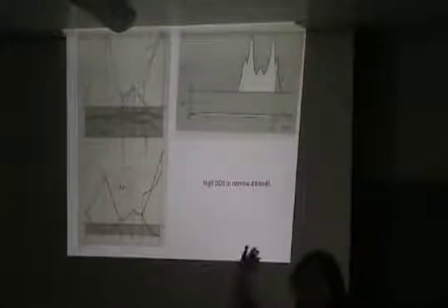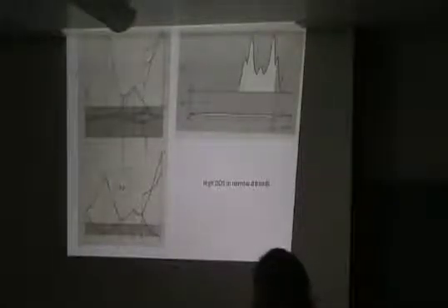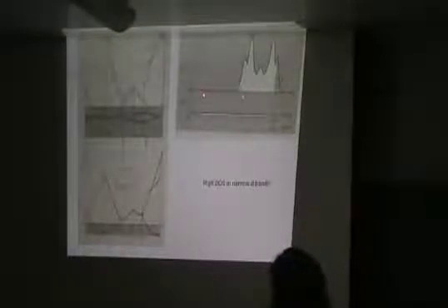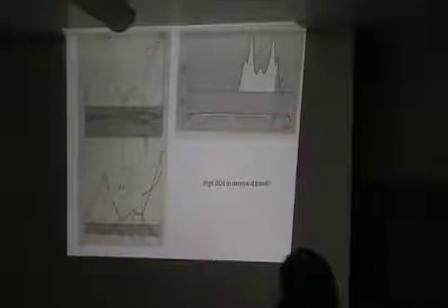And the density of states, right? If I have a lot of bands in a narrow energy range, the number of states per unit energy will be very large, because it's a density. You can see that the density of states for the S band goes like the square root of E, which we derived. It's a very shallow square root of E, whereas the D bands exist in a very narrow window and have a lot of structure.